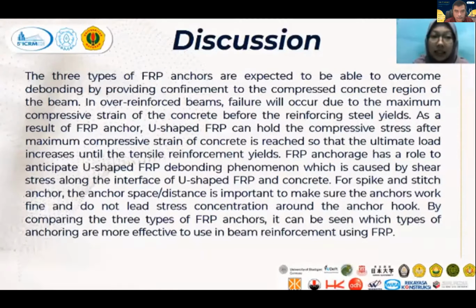Discussion. The three types of FRP anchor are expected to be able to overcome the debonding by providing confinement to the compressed concrete region of the beam. In over-reinforced beams, failure will occur due to maximum compressive strain of the concrete before the reinforcing steel yields. As a result of FRP anchor use, FRP can hold the compressive stress after maximum compressive strain of concrete is reached so that the ultimate load increases until the tensile reinforcement yields. The FRP anchor has a role to anticipate the FRP debonding phenomenon, which is caused by shear stress along the interface of U-shaped FRP and concrete.